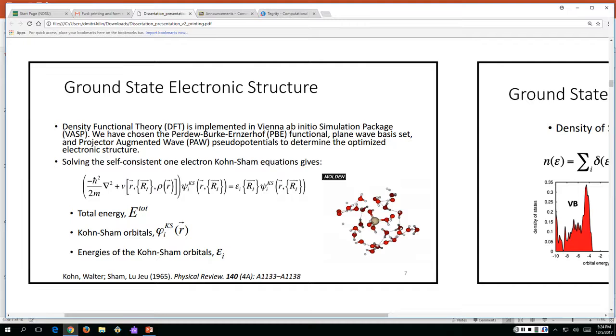What do you mean band structure shape? Well, so if you have some sort of, so you have a creation of an exciton, right? And so as somewhere they may, well, maybe that's not the right way to put it. So depending on the spatial confinement, right, if you get them somewhere reasonably close, you can have a larger overlap of the two exciton particles. And so you would have some type of faster radiative transition, right? Because if you have a larger wave function overlap, you're going to have a larger oscillator strength.